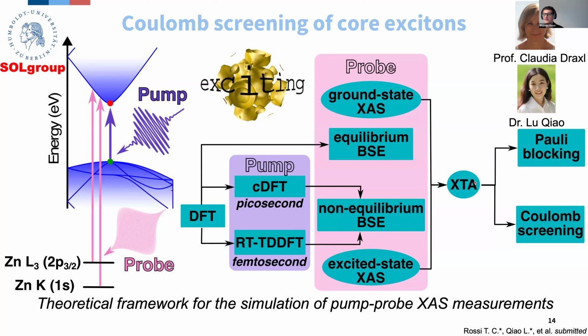And the novelty in this work is that we were able, with this exciting code, to disentangle many-body contributions to the pump probe spectrum. In particular, there are two many-body contributions that are extremely important. One is the Pauli blocking, which is the effect of carrier populations on blocking X-ray transitions. So it's basically based on the Pauli exclusion principle, although there are some contributions from the exchange interaction in it as well. And the other one is the Coulomb screening. So the fact that the photoexcited carriers actually bring a Coulomb field with them, and this Coulomb field is going to screen excitonic interactions. So that's basically the theoretical framework we used.